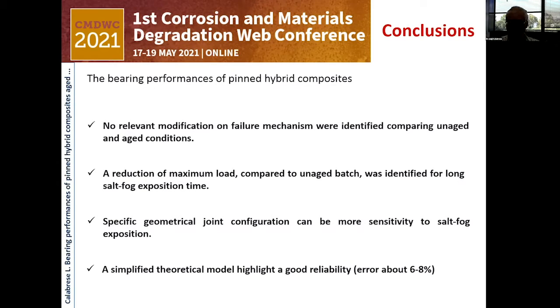In the meanwhile, the ageing contribution plays a relevant role in the degradation of the joint, and this degradation influences the complex failure mechanism that occurs in the pinned samples. And in this case, the theoretical approach that we applied required the addition of an additional parameter related to the degradation index that required to be supported by experimental data. But anyway, by adapting this approach to the ageing information, it is possible to have a theoretical model with reliable performance.